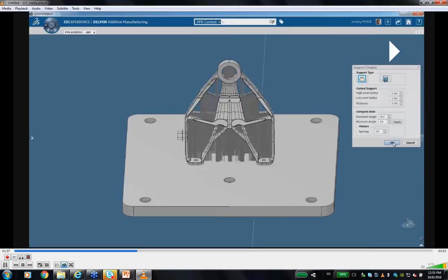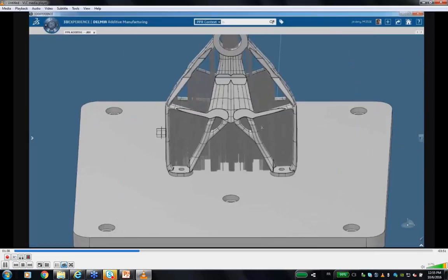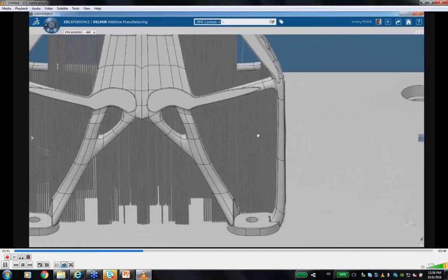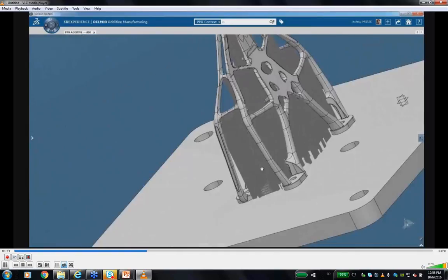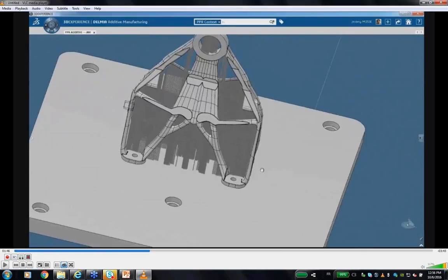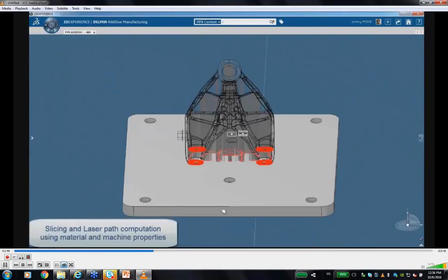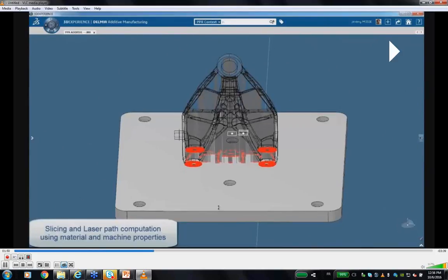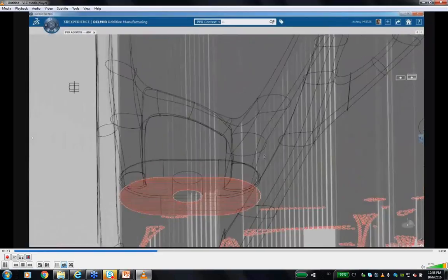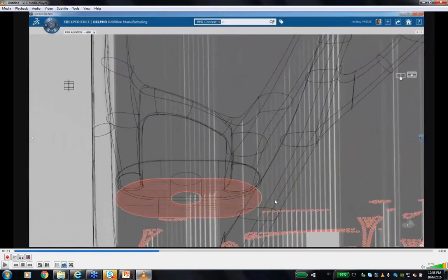So what is it? We now have a solution to slice the part and the support, but not only slice. Some machines, for example like EOS, do not like the outer shape of the support and the part. They prefer slices. So we could do that. We could slice and then send the data as a CLI format to the EOS machine, but we can do much more. So we slice, but we also select among various lasing strategies the one which is the most appropriate to our process. Here you can see there is contouring for every single plane. We create contouring of the sections, and maybe we create this type of back and forth lasing strategy.